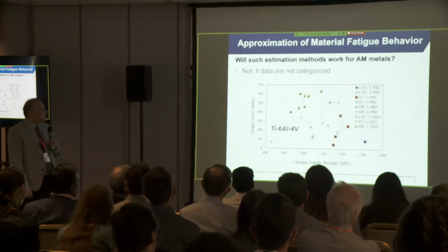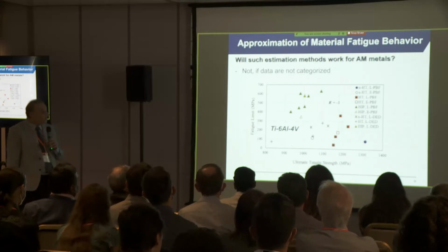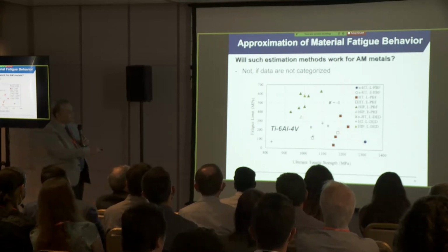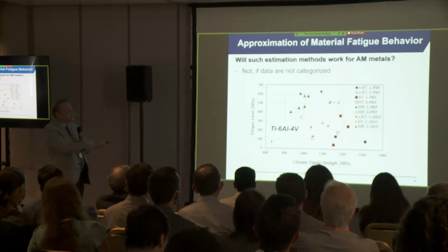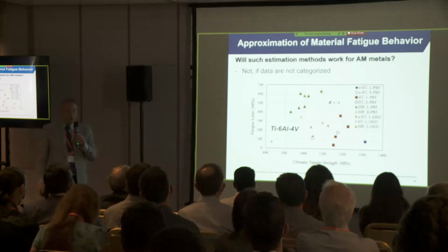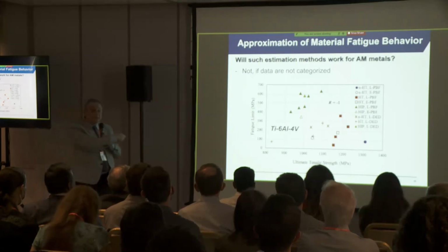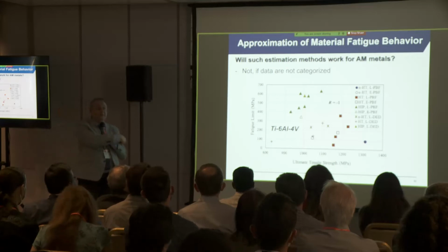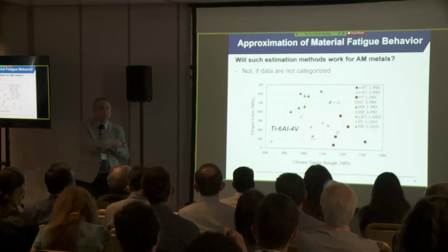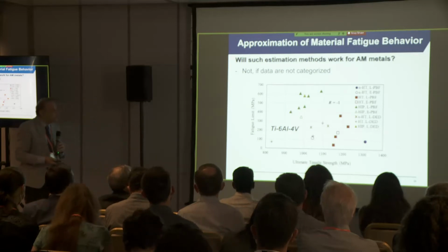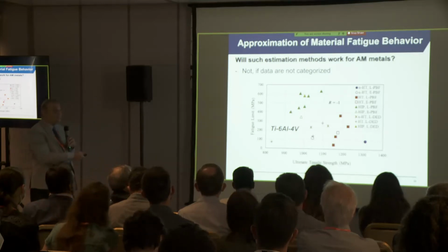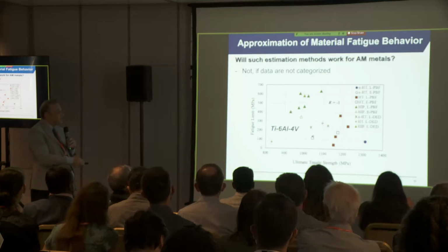Do they apply to additive manufactured data? Well, here is a plot of fatigue strength versus tensile strength. You see, there is no correlation at all because of all the variability I talked about earlier. Defects, surface roughness, residual stresses, and their variability through the component, you don't really get a correlation between fatigue limit and tensile strength.